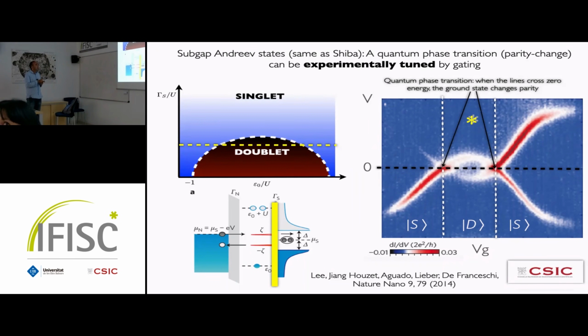I was involved in some theory with them. Essentially, the idea is that you can now excite these Shiba excitations in the singlet, by putting an electron here, which is reflected as a hole by an Andreev reflection in this superconductor. You put a Cooper pair. So essentially you can measure excitations in dI/dV, in transport, and you see these excitations in the system as peaks. This red line here, in this contour plot of the derivative dI/dV, is essentially a peak in conductance, okay?